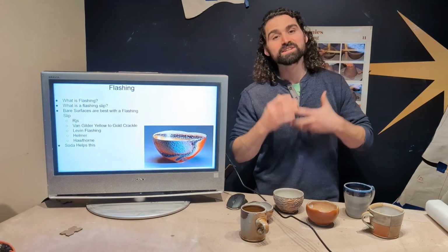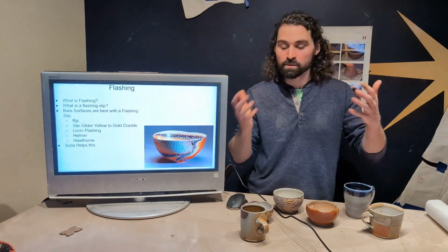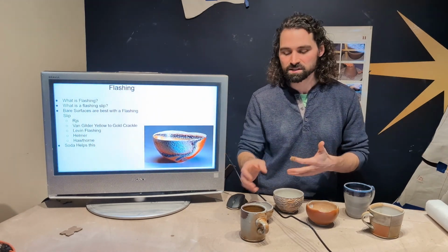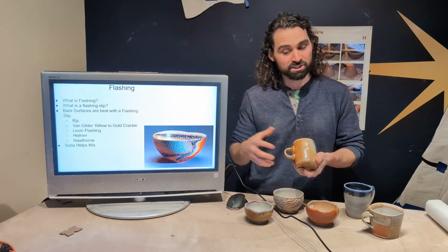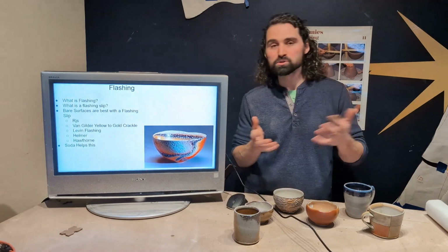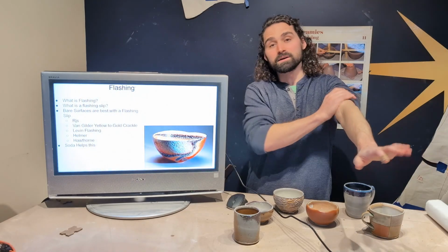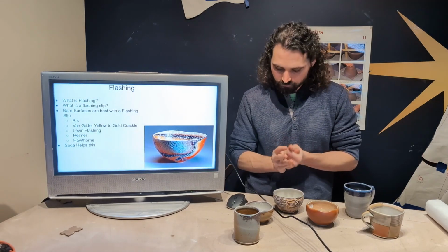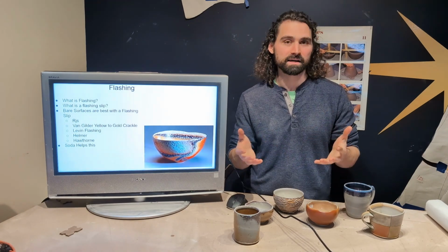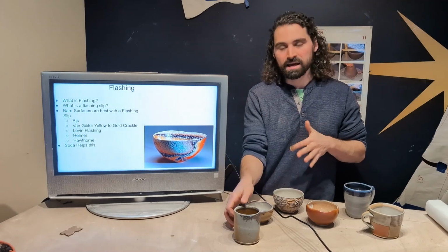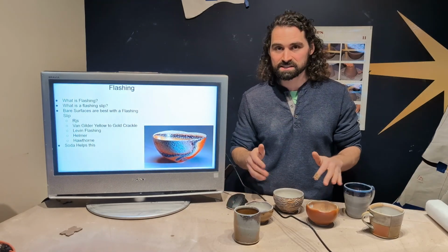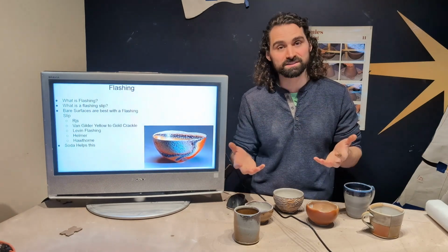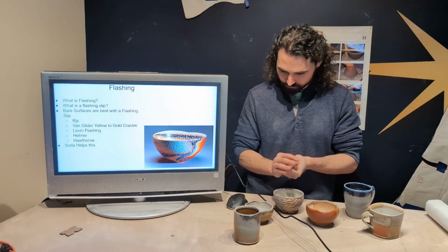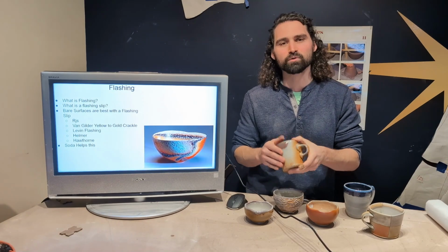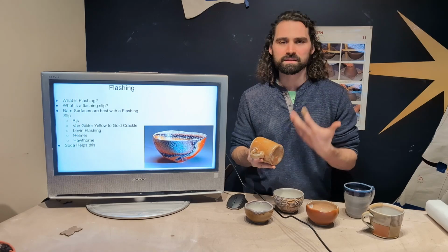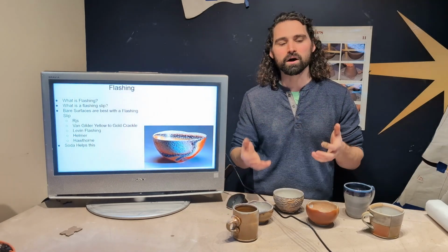What are flashing slips? Flashing slips are just clay slips that we put on the surface of our pieces to bring out better flashing. Some clay bodies flash, most do to a certain extent, if they have any other additives in them, like iron or whatever. What I have found works best for most firings is using the regular B-Mix 10 and putting a flashing slip on that, if that's the kind of surface you want. Because they're formulated to bring out that flashing, they're going to be better than the clay bodies themselves, and we will have other options.